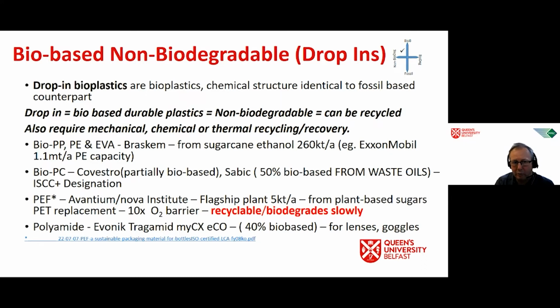Other drop-in plastics, bio-based, non-biodegradable would be biopolycarbonate, bio-PC, which is produced by both Covestro, which is partially bio-based, and also SABIC. Again, this is 50% bio-based, but in this case, it's from waste oils. And the SABIC bio-PC has an ISCC Plus designation. Another material is PEF, a new material which I'll go into in a little more detail, but it has a flagship plant in the Netherlands, producing 5 kilotons per year from plant-based sugars.